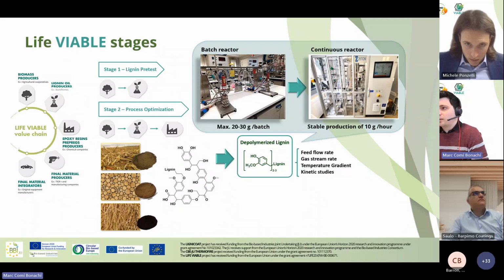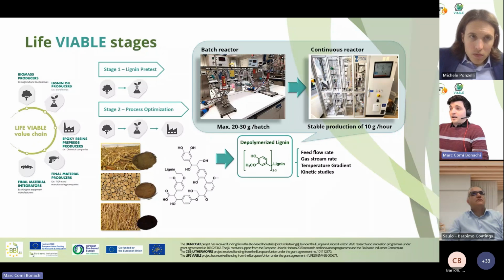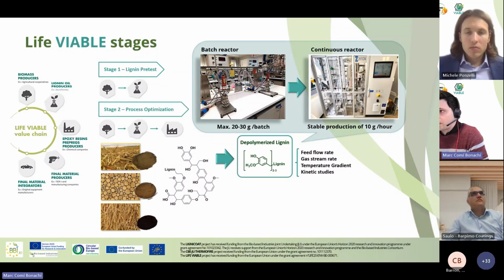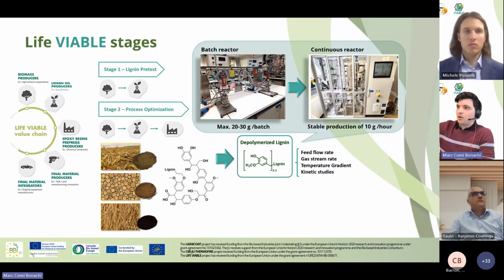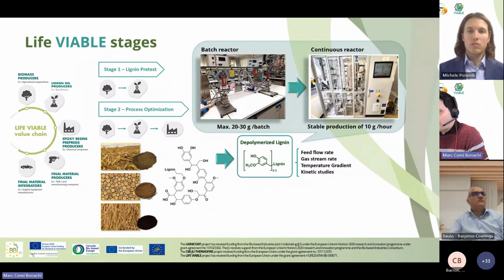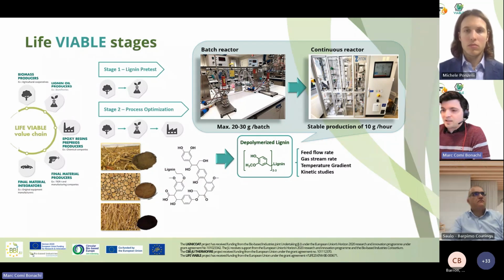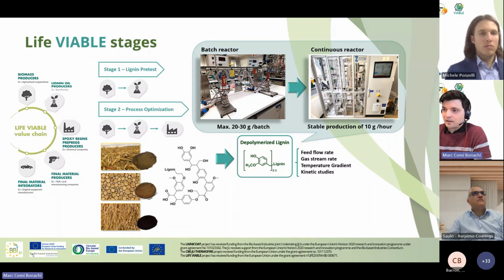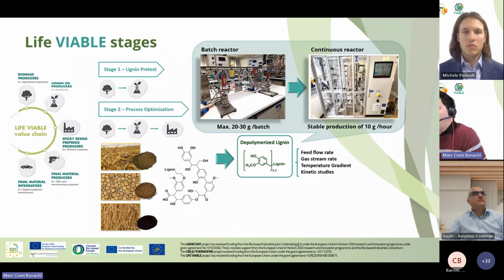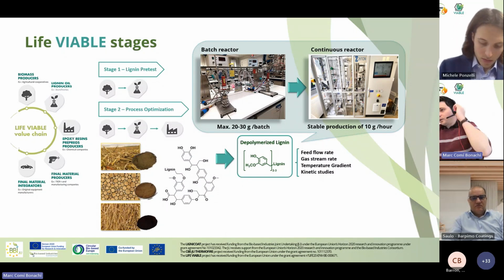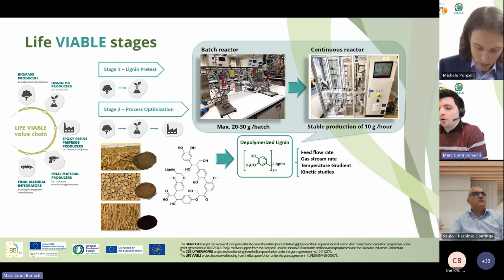Here also, in comparison with the batch reactor, we can play with the temperature. We don't need to maintain the same temperature always. In different parts of the continuous reactor, we can apply temperature gradients that allow us to target different ether bonds inside the lignin molecule. And also, a big difference between the batch reactor and the continuous reactor is that we can monitor what is happening inside the reactor at different times.